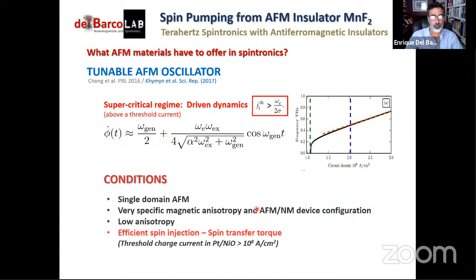All right, so this is very nice. So what do we need in order to realize that? I'm not going to demonstrate this today, but this is what is driving our team, right? Well, it's not easy. We need to work with single domain antiferromagnets. Those are not really trivial to obtain. We need a very specific symmetry of and relation between the magnetic anisotropy and the device configuration. The spin current should be polarized in a particular direction with respect to the anisotropy axis. We really need to decrease the anisotropy because we need low threshold currents. For example, and at the same time, we want to increase the efficiency in injecting spin into the antiferromagnet.